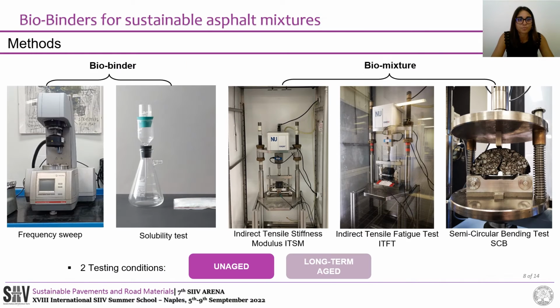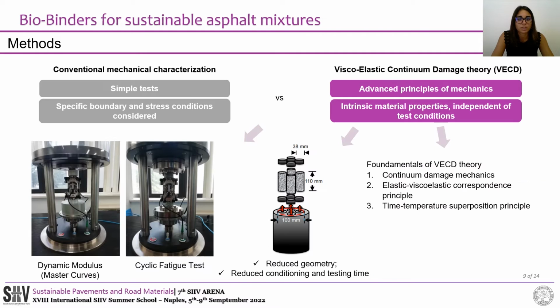A similar approach, consisting in frequency sweep and solubility test, was adopted for the rheological and chemical characterization of bituminous binders, as well as the same conventional mechanical characterization was reproduced on asphalt mixtures. Moreover, a more advanced mechanical characterization of asphalt mixtures, consisting in the viscoelastic continuum damage theory, was also performed, consisting in master curves and fatigue tests.